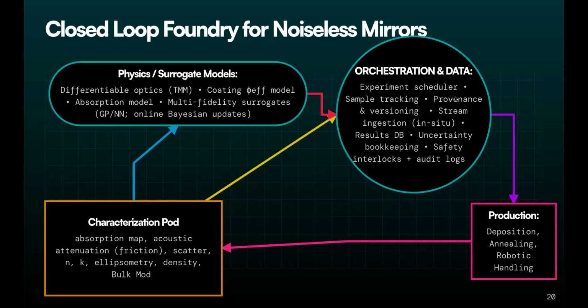And we've tried all kinds of things like annealing and trying different compositions and different metal oxides. But the issue is the process is really, really slow. And none of this exists. So we have deposition and we have some characterization, but this process takes, let's say, a few days at best, because you have to grow the film slowly. You need to make a stack like that picture I showed. So at the best, it's like 3 days or something to grow a film. And then the manufacturer usually does some characterization too. And then you ship it to a bunch of university labs. And depending on the grad students, how they feel that day, and whether I have funding or whatever, that's a year.